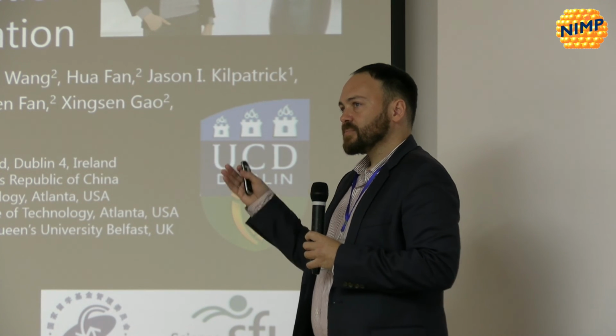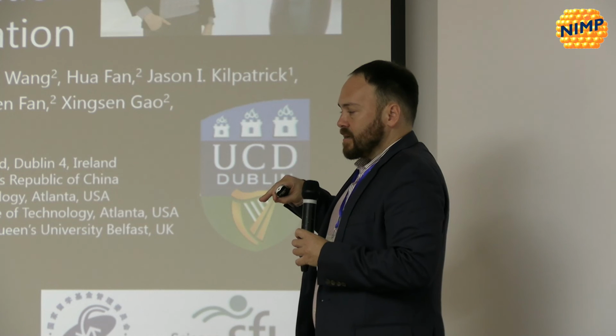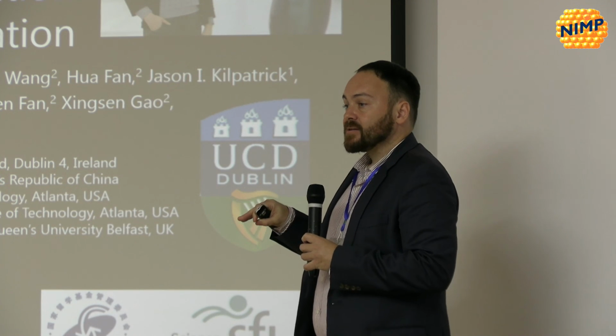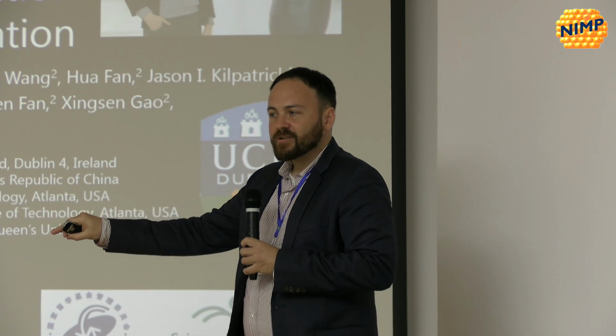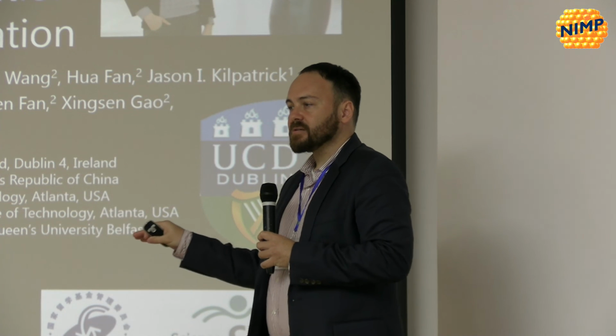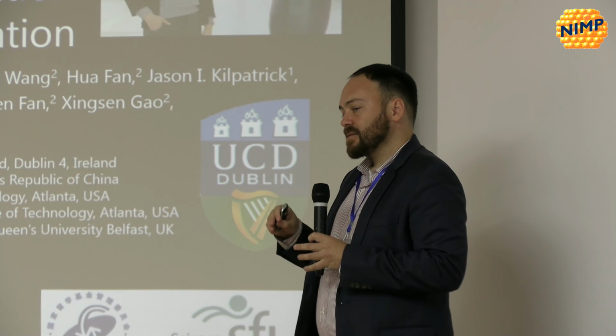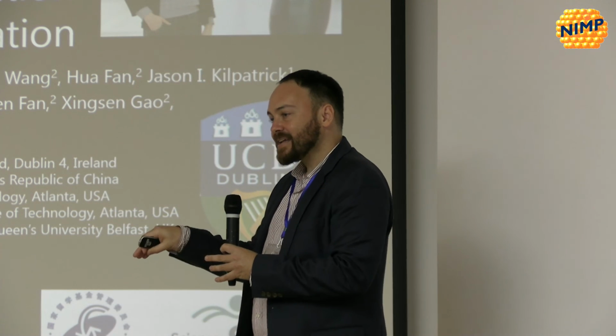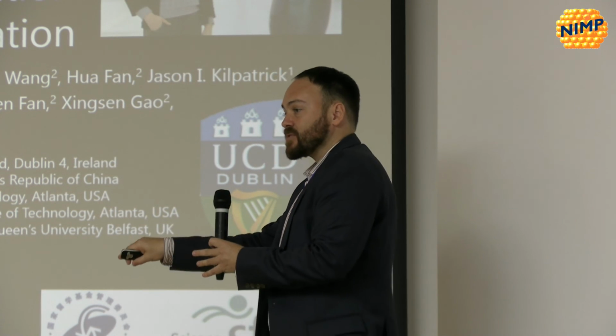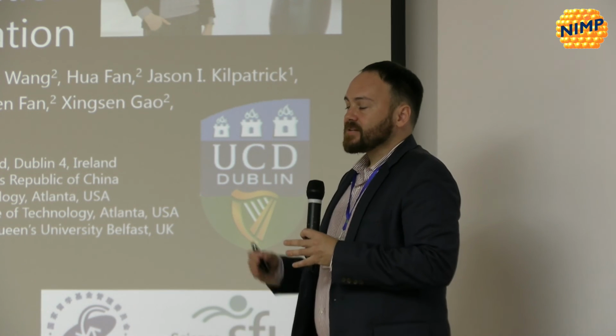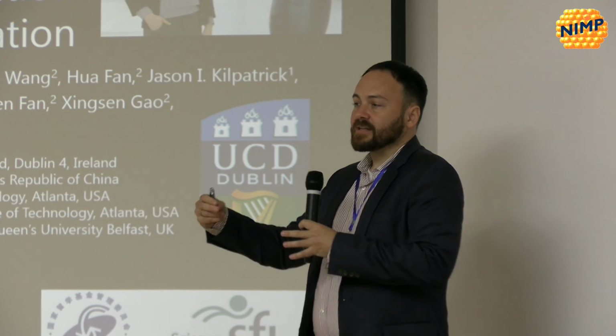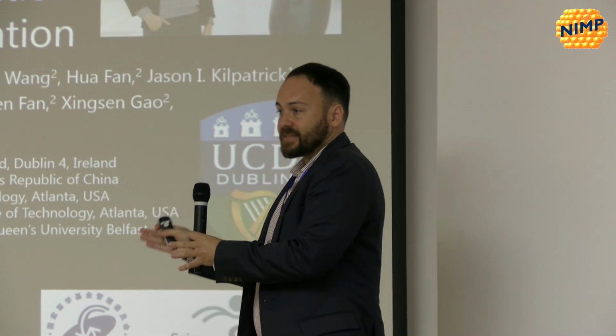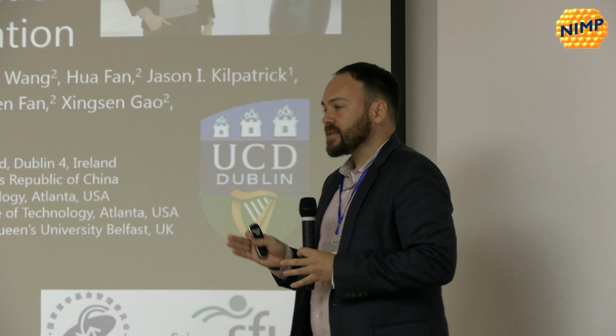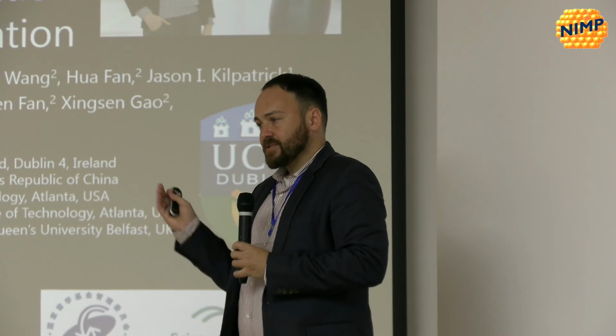And perhaps you noticed that when we were doing the scan angle study, it wasn't always along zero that was the best. It was a little bit off zero. So that could be because basically the material has to fracture, it has to break a little bit. And when that's happening, there's a little bit of twisting. So the tip is going in a certain direction. There's the possibility also of a slight offset in terms of placing the cantilever. It's not always perfect. But we did notice that the tip tends to move in a certain direction at the beginning, and that shows up in that.